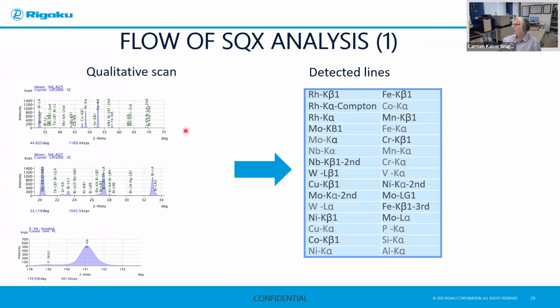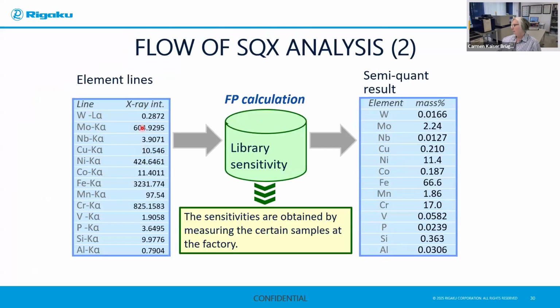So if you look now, this is an example of a semi-quantitative analysis. This is the example of a qualitative scan, and this is the detected lines. You can see we have L lines, we have K lines, we have alpha and beta lines. These lines have been identified, and once they've been identified with a clear peak, which is done automatically by the software, these will be measured for the intensity. Each line will be measured with an intensity, and these intensities from the unknown sample will be used with the sensitivity library to calculate, using fundamental parameters, what the concentrations of the elements will be. The sensitivities that we obtain in this library are set up by the factory.